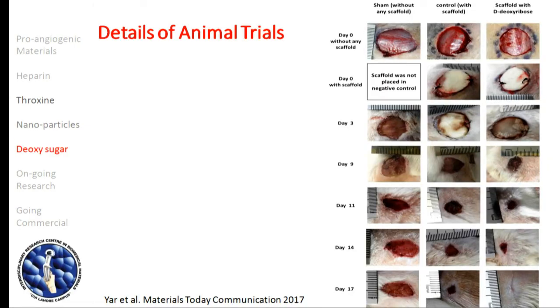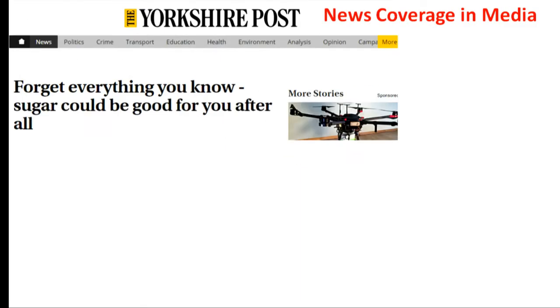On day 17, we can see that in the sham, where we haven't applied anything, the wound is still there. With the scaffold control, that's the simple chitosan collagen membrane, even the middle one is not closed, but the one with the sugar is closed very well. This is showing the strength of this technology, that the wound has been closed very well. So there was good media coverage on this.